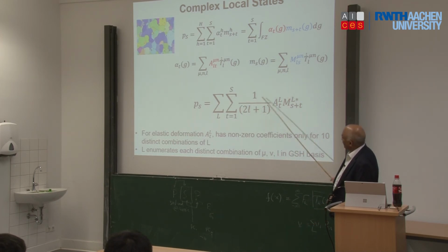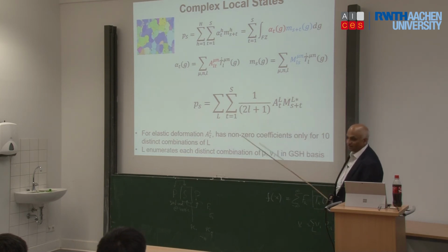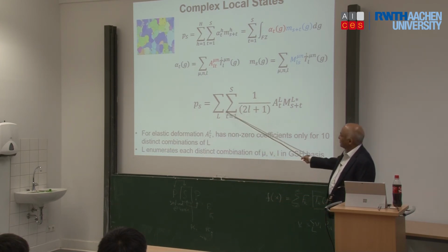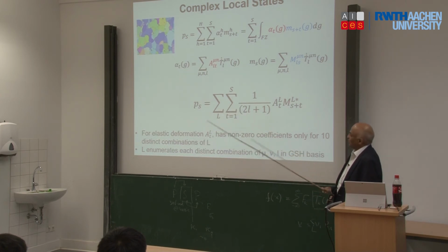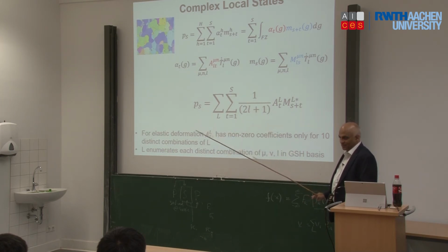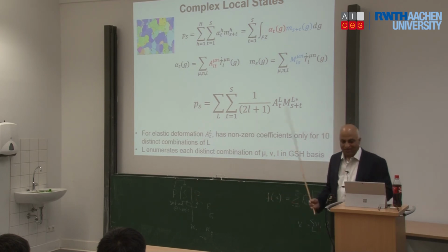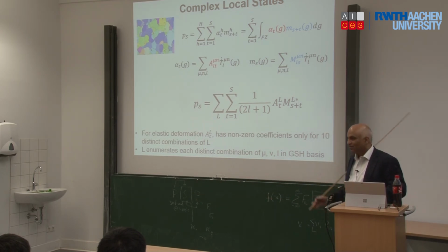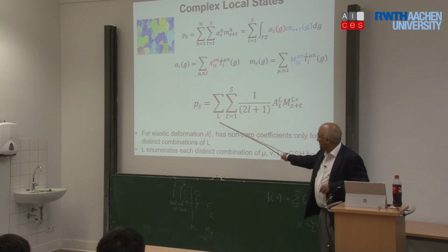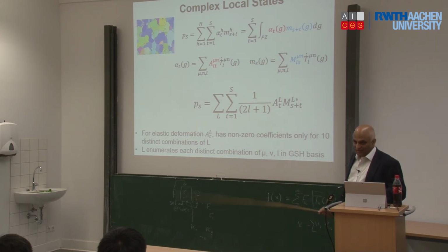The advantage of this is that this coefficient, so this one can be anything it wants, but this coefficient for elasticity, you can actually theoretically prove that for example, for cubic metals, only L equal to 10 are non-zero. Everything above that has to be 0. So there are some of those theorems that actually work out, and so I can represent this in a very compact way. In fact, there is no other compact representation for this term other than with spherical harmonics. Spherical harmonics give you the most compact representation of this term. And you can actually theoretically prove it for elasticity. For other ones, you cannot. I mean, at least we haven't figured out how to do it, but others might have. So that's the answer to why we do spherical harmonics. The number of terms here is the minimum you can get in this particular case. In the elastic case, it's the minimum.